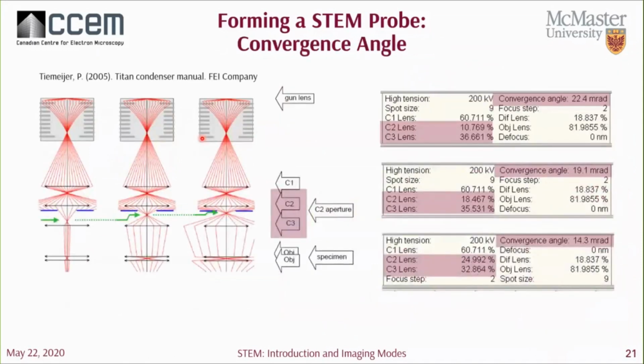Now, the final step in converging is to converge the beam into a probe on the specimen. We do that by changing the C2 lens and also the resulting C3 lens. As we increase the strength of the C2 lens, there's a further demagnification of the image between the C2 and the C3 lens, shown here. So strengthening of the C2 lens decreases the convergence angle.